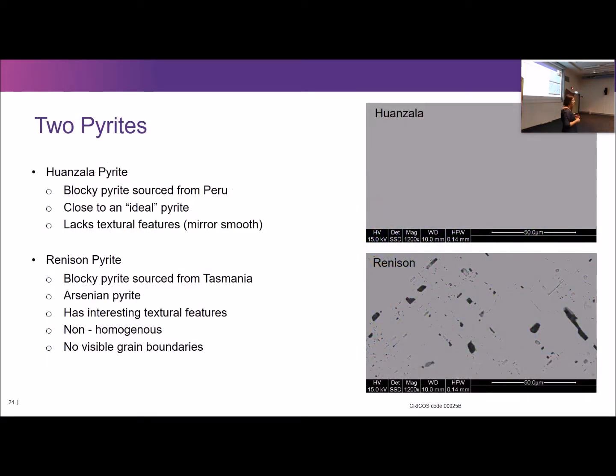So let's just sum up. Two pyrites. Huanzala pyrite, sourced from Peru, is close to ideal pyrite, probably as close as you're going to get to an ideal pyrite, and it completely lacks features. Renison pyrite is also a blocky pyrite. Sourced from Tasmania, it's an Arsenian pyrite. It has some very interesting textural features. The distribution of arsenic is non-homogeneous but relatively pseudo-random, and no visible grain boundaries between high and low arsenic regions.